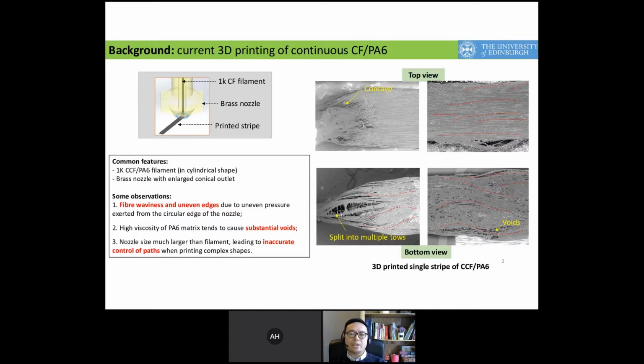When printing in a straight path, the nozzle presses on the filament and changes its shape to a strip. This process causes a non-uniform pressure distribution and therefore fiber misalignment in the strip. The fibers could also be split into multiple tows due to the large tension at the bottom of the strip. Substantial voids may occur due to the high melt viscosity of the PA6. Because the filament is much smaller than the nozzle, it wobbles in the nozzle, which makes it more difficult to achieve accurate print passes.